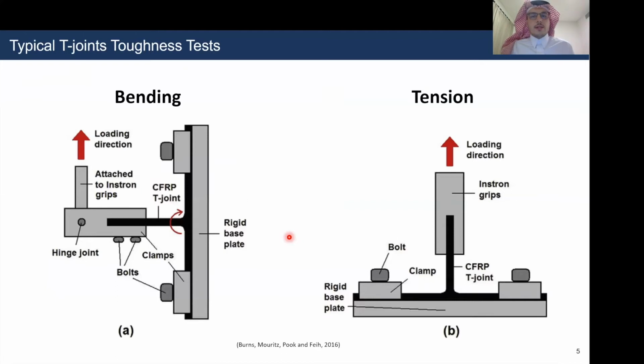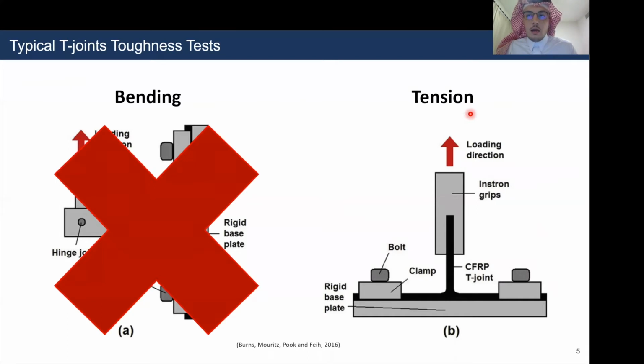So typically in T-joint structures, there are two different toughness tests involved. The first one is a bending test where a monotonically increasing load is applied perpendicular to the stiffener. So the stiffener is actually held sideways and the load is applied perpendicular to the stiffener. The second test is a tension test, which involves having a boundary condition where the skin and the stiffener are clamped on the bottom and the load is applied in tension in the same direction as the stiffener. So for this study, I will focus mainly on the tension. I'm not going to go over the bending.